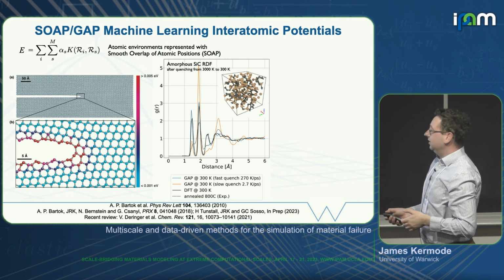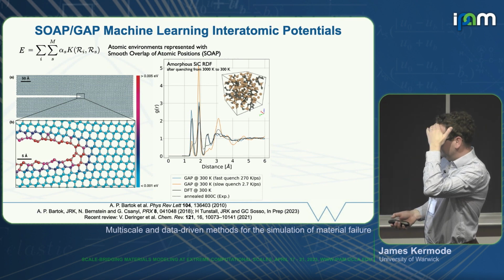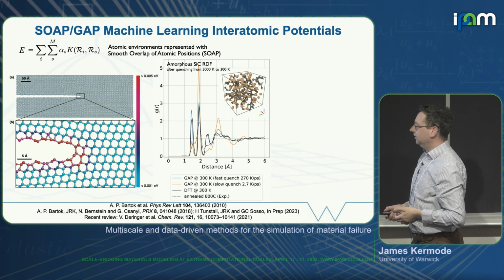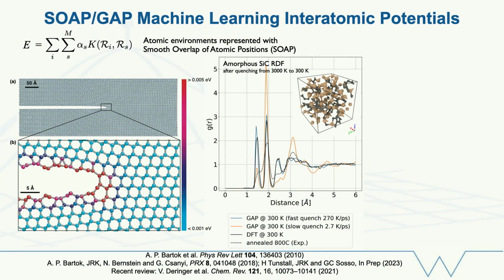I wanted to briefly mention another GAP that has been fitted in my group by Harry Tunstall, just to show the kinds of things that you can do. So this is multi-species, two species, it's silicon carbide. And what we were pleased with here is that we could quench it very quickly. So we could go from 3000 Kelvin down to 300. And in that case, we get the blue curve, which matches up rather well with the density functional theory radial distribution function that characterizes the structure of the amorphous, because in DFT you have to do it fast. You can't afford to do a super slow quench.